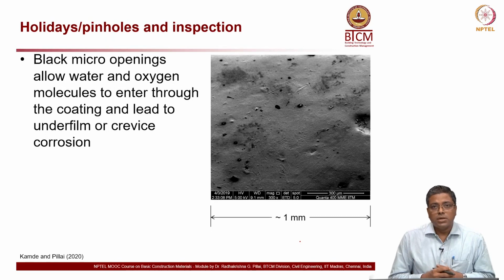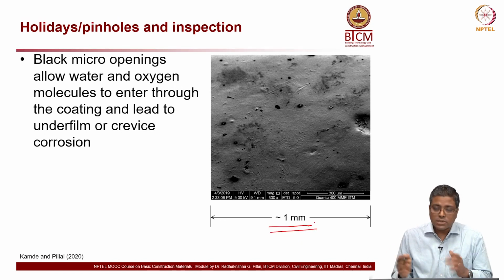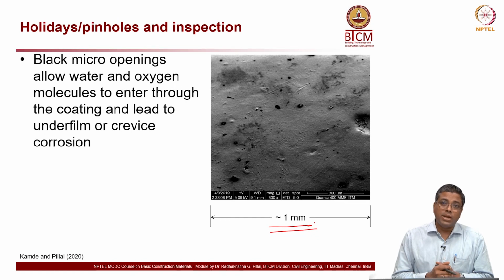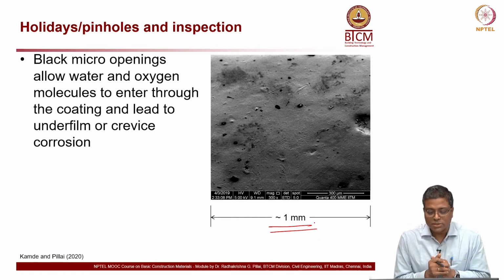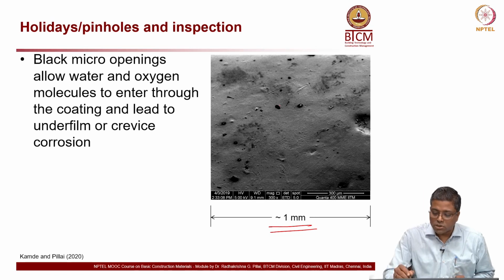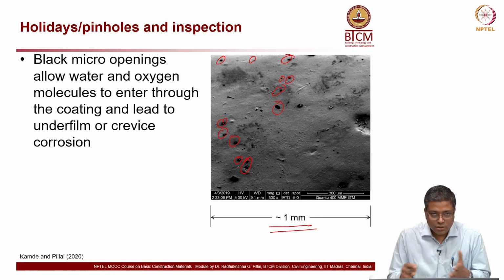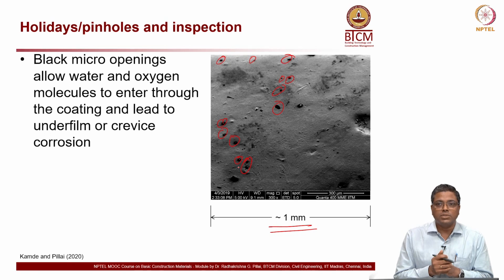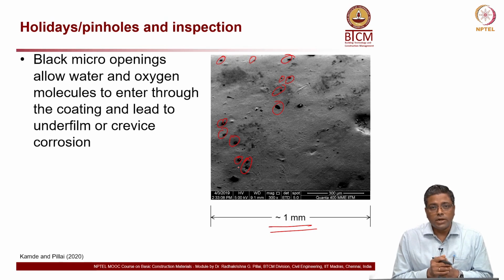Now the problem is most often there could be holidays or pinholes, and this picture on the right side is a micrograph. You can imagine the size of this micrograph is only about 1 millimeter. In that small size, you have so many of these black spots, through which water molecules, oxygen, etc. can penetrate. This surface looks gray because you are looking through a microscope, so it is in grayscale. But the point is that you can have a lot of these pinholes or holidays on the rebar surface.